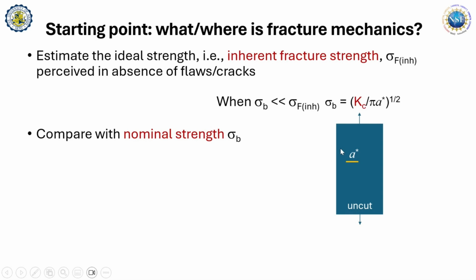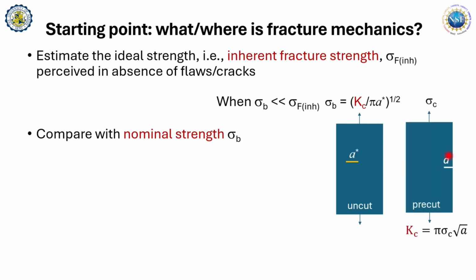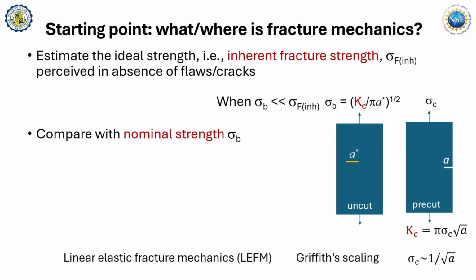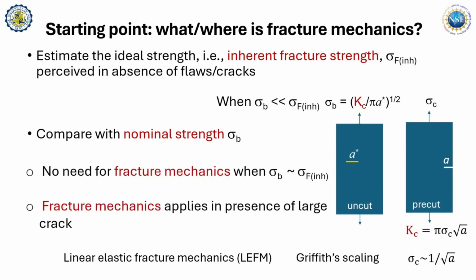In fact, the whole fracture mechanic discovered that you can take an experiment like this by making a large notch and measure the critical load at which fracture occurs, and you obtain Kc. Then you plug it back to the first formula, you have a sense of how the strength is lowered. And that's the fracture mechanics. From this, you can see the famous Griffith scaling law holds because Kc is a constant. As I said, you don't need fracture mechanics if they are comparable. Conversely, when you have a large notch, not large crack, that's where you apply fracture mechanics.